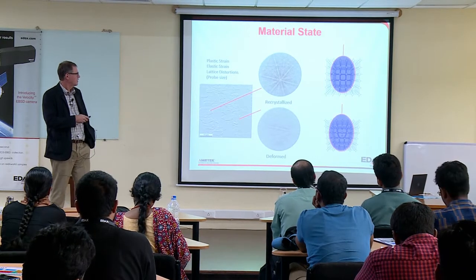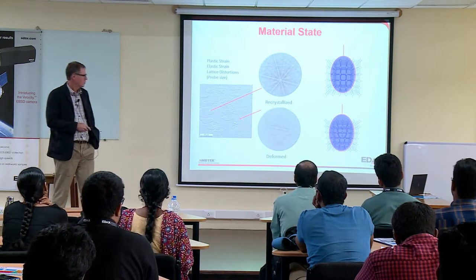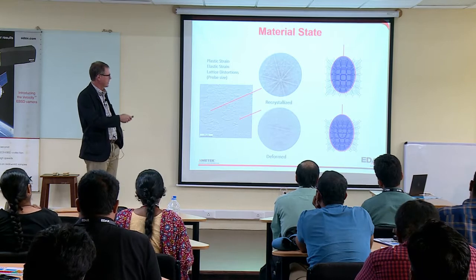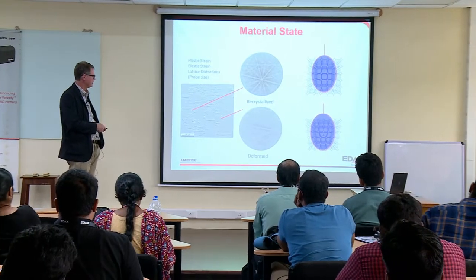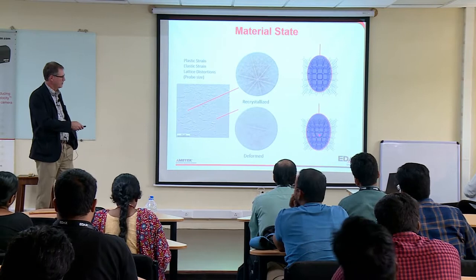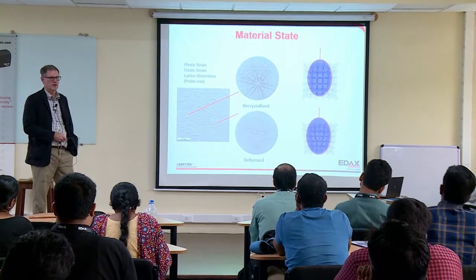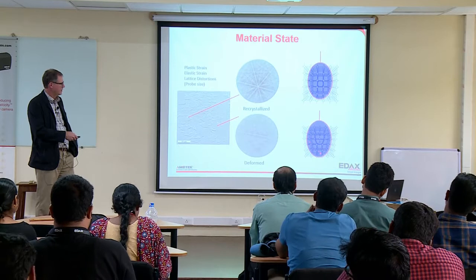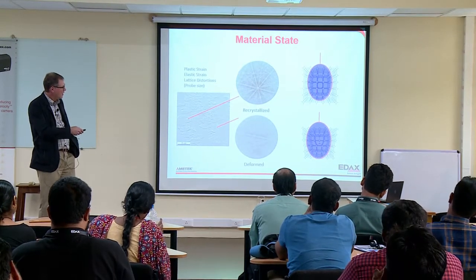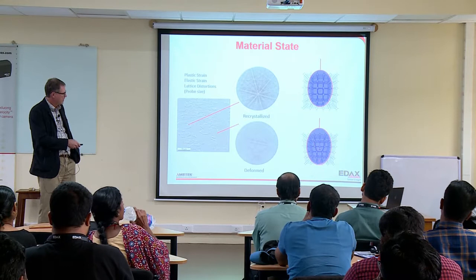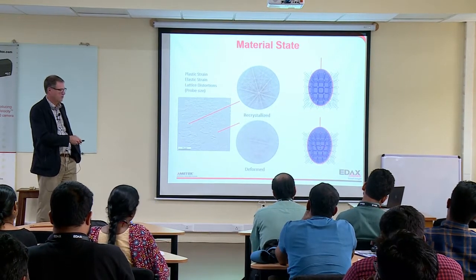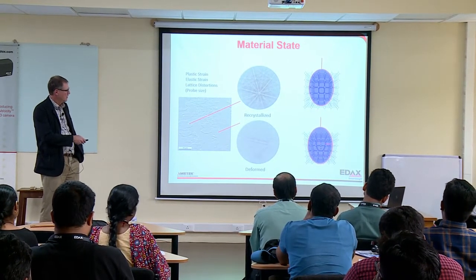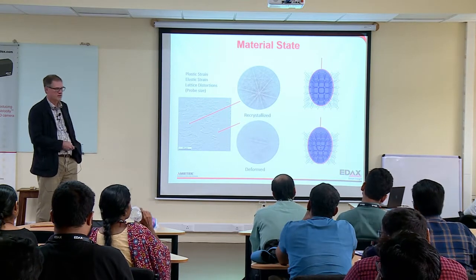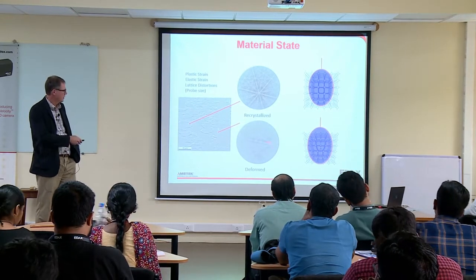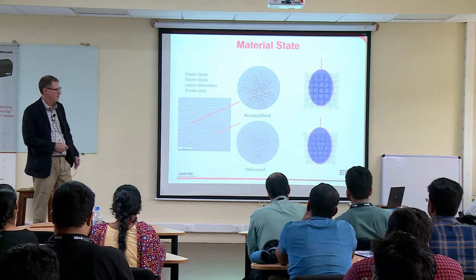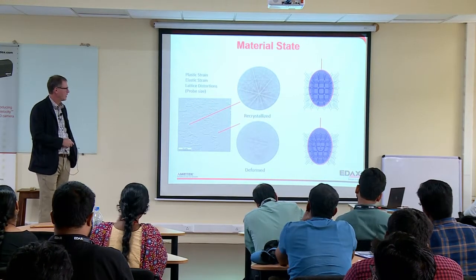Why does that happen? That's because of deformation. So if you look here, this is greatly exaggerated. The interaction volume is much bigger than this, but just to show an example, if I have a dislocation in my material, I've disrupted the atomic lattice. And now, instead of satisfying Bragg's law on a single plane, Bragg's law is actually kind of shifting as it moves around here. So I have electrons satisfying Bragg's law at several different angles or orientations, and so I end up with a smearing of the patterns. And that's one effect you can get.